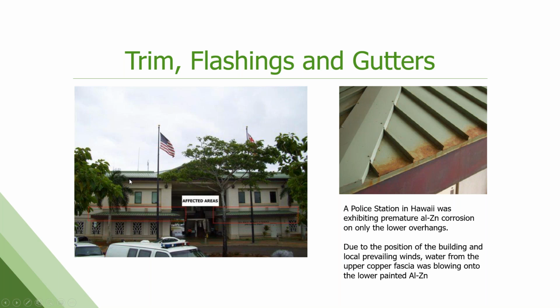So the water was blowing off of the top copper fascia onto these panels and running to the edge and sitting, and we had galvanic corrosion occurring, and the galvalume was sacrificing itself for the copper. So that was an odd one. Took us a while to figure out what was going on at first because it wasn't on the same plane where the root cause was up above.